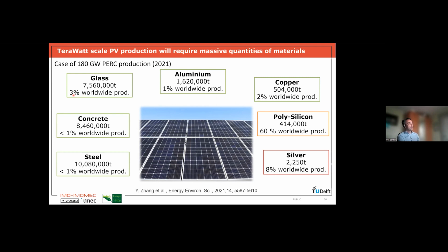And you see also, in percentage, how much of the worldwide production of this material was needed for 180 gigawatts. And the main bottleneck is actually the silver. We use only a few grams of silver per module, but because we produce almost 1 billion modules, this is actually a very large number. And for this 180 gigawatt of PERC, it already corresponded to 8% of the worldwide production.